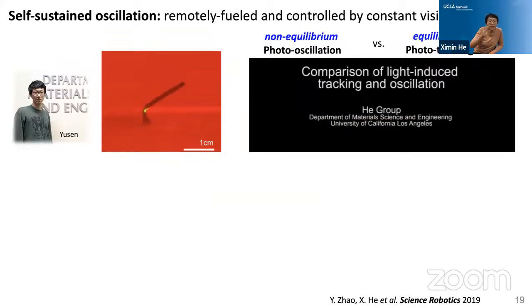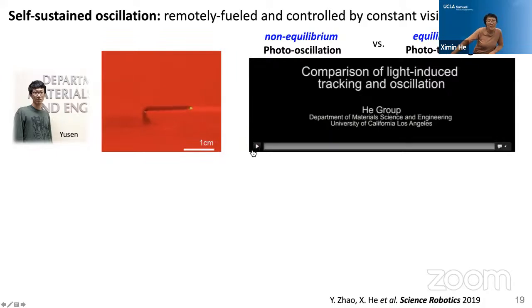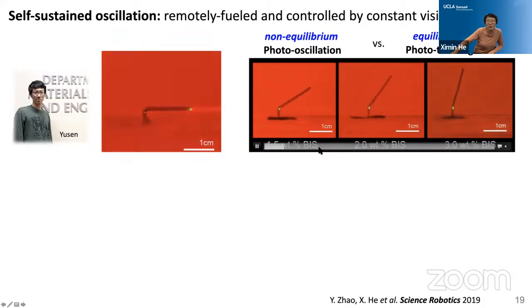All right. So interestingly, during this work, one of our students recently found sometimes this pillar does not always just steadily point to the light. Sometimes they actually oscillate around the optical beam. So to verify this is not some accidental vibration from the environment, we basically tune this crosslinking density of hydrogels so that some more active responsive hydrogels tend to bounce around and oscillate, and those slowly responsive gels tend to perform this steady